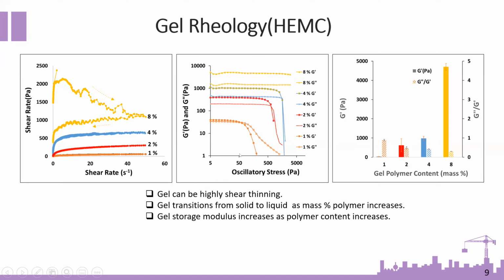We also performed oscillatory measurements of the hydrogels. As you can see here, except for the 8% gel, for all of the concentrations we have a yield point where the material transitions from solid-like to fluid-like behavior. But as we move from 4% to 8%, we no longer see the transition from solid to liquid-like behavior.